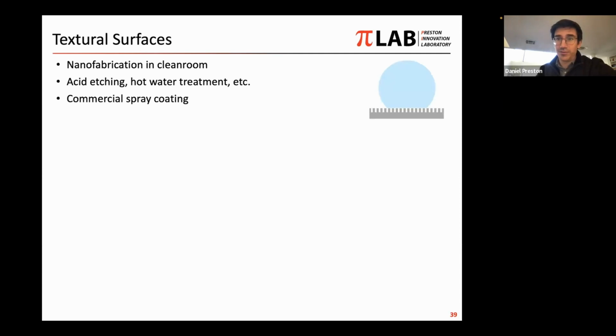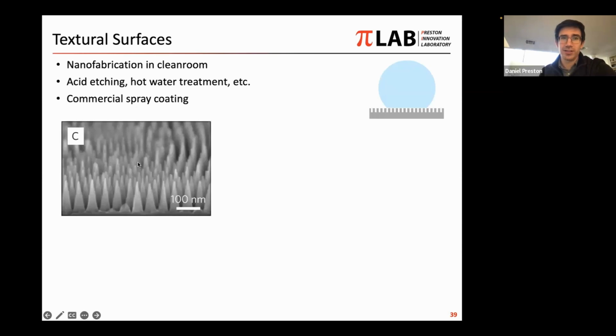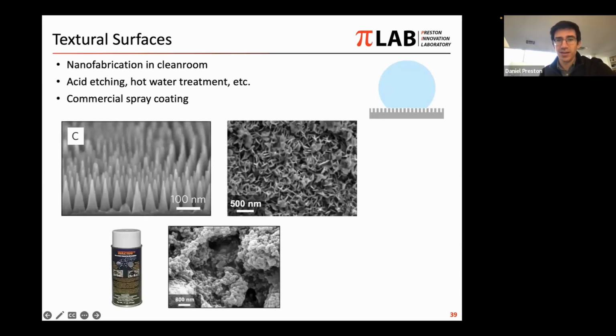And so there are a lot of approaches that we can use when we try to make engineered bio-inspired solutions that include things like nanofabrication, maybe also etching of the surfaces. So I showed that for our aluminum ultra clean storage containers, we just use a hot water treatment. That's an effective way to get some nanostructures on the surface. In that case, those nanostructures would be hydrophilic, and we would still need to apply a chemical coating to functionalize or make the structures hydrophobic to achieve super hydrophobicity. And then alternatively, there are some commercial spray coatings that are just off the shelf. And so I show here some of the nanofabricated, some of the hot water treated surfaces, and then also the spray coating approach. You can just buy a spray can and spray it onto the surface, and it forms these nice structures, which are also already chemically hydrophobic to achieve superhydrophobicity.